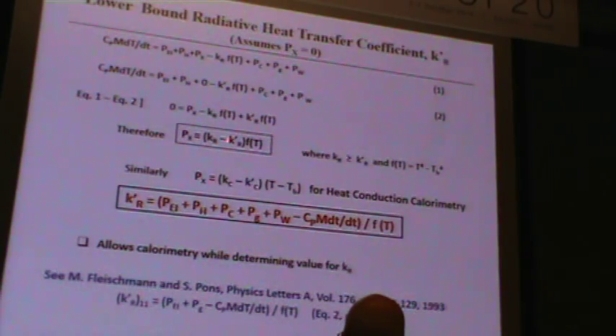This is actually as good as you can do if you use the differential equation. You just calculate the constant based on assuming no excess power. A little error here, if this is radiation here, that has to be power due to radiation here. But you can do calorimetry without knowing your cell constant. You can calibrate as you go, and the highest value you get for the constant, assuming no excess power, will be close to the correct cell constant.